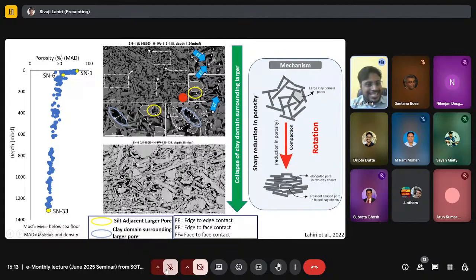Now this is the sample SN6 from 28 meter depth. Now, interestingly, within this sample, we dominantly observe this kind of face-to-face particle contacts. However, edge-to-edge and edge-to-face particle contacts are very rare here in this sample. Nevertheless, if we try to look at the pore structure here in this sample, we dominantly observe this kind of silt adjacent larger pores. However, this type of clay domain surrounding larger pores is very rare in this sample.